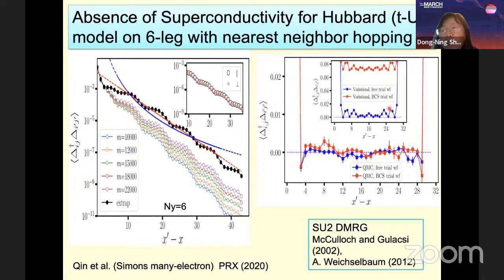A simple way is the mean field, slave mean field approach. Yes, it does give the D-wave symmetry, because the D-wave symmetry has an additional parameter, like in the X and Y direction you can have different sign of pairing that allows you to get better variational energy.